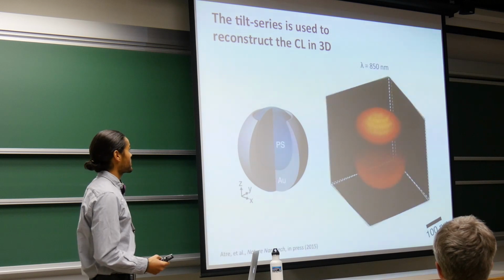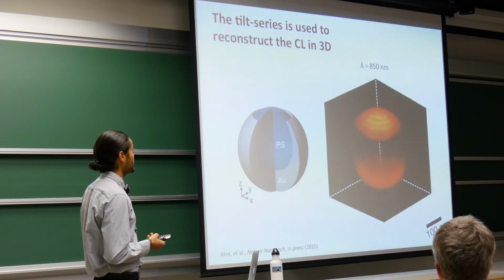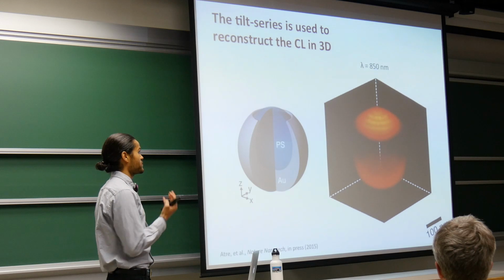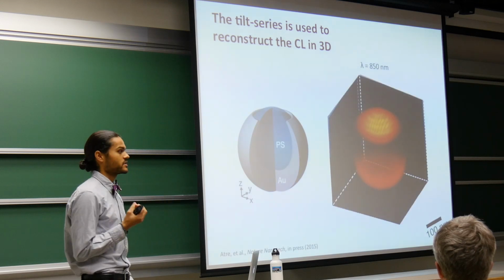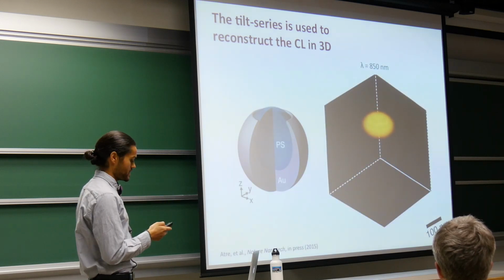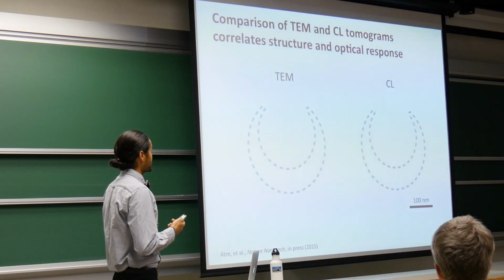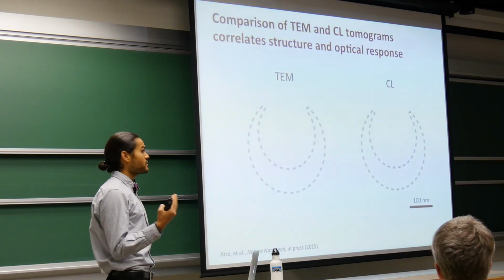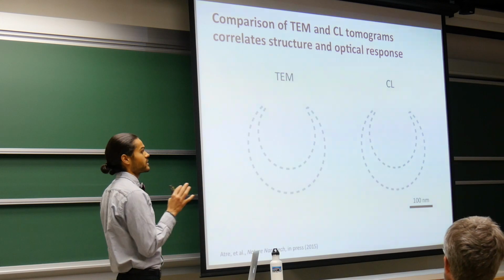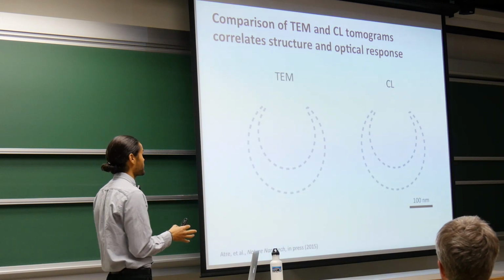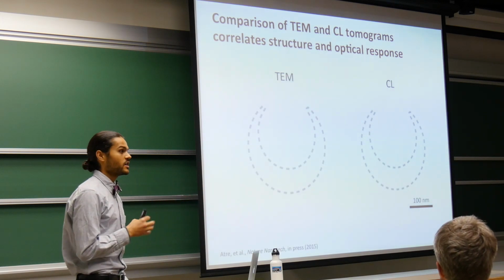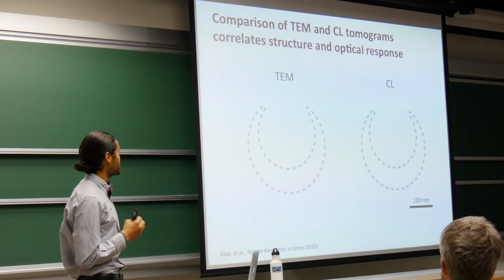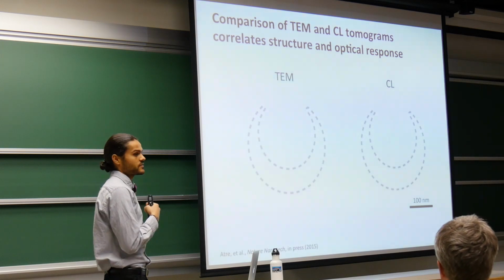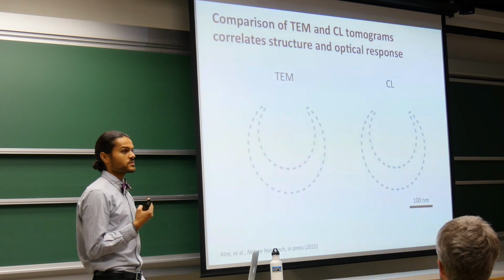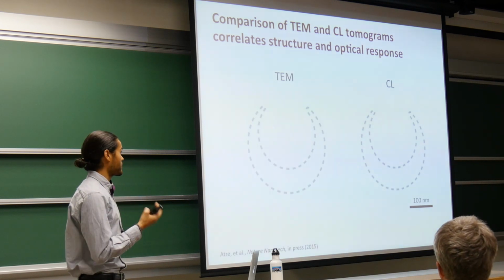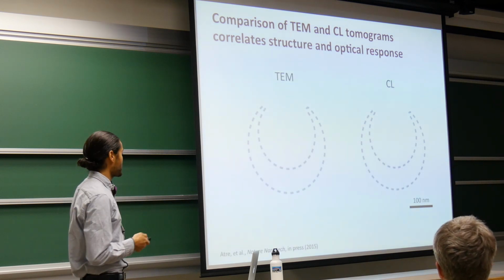So here is the cathodoluminescence tomogram at 850 nanometers, which just shows you the strong signal localized to the tip region. Looked at in a slightly different way, we can fly through the crescent, and here I'm going to be comparing the reconstructed cathodoluminescence signal on the right with a TEM reconstruction based on that tilt series that I showed you in the very beginning, where the darker colors of the TEM reconstruction correspond to regions of higher atomic mass, so that would be the gold.